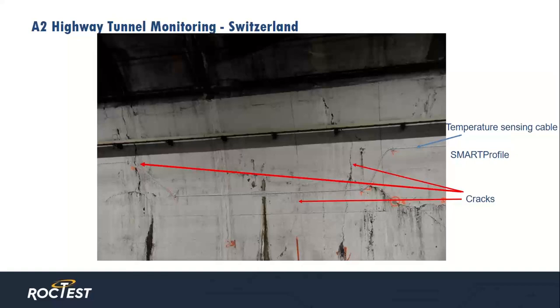Okay, so in the photo here, you can see one line of smart profile fiber optic cable. You can see that called out in blue. Any deformation or crack formation due to hydrostatic pressure behind the lining would easily be detected. It's also worth noting that because, again, distributed fiber is very flexible, has a small bend radius, you can bend the fiber to any shape you need. Versus simply having one solid line of fiber, we can shape it. So you can see here that we've bent it to cross over several crack areas called out in red.